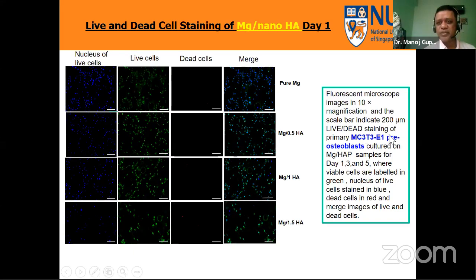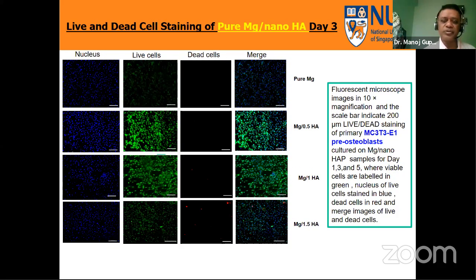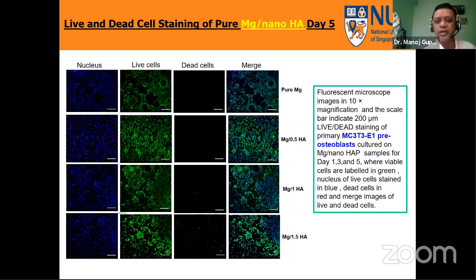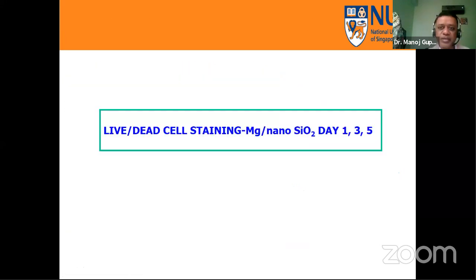Again using the MC3T3E1 pre-osteoblast cell line, all compositions show a very good presence of live cells. This is day 5 for nanohydroxyapatite, and apparently the best density was again for 0.5 HA and 1 HA. But 1.5 HA, shown in the bottom picture, is also very reasonable. Still, when compared, 0.5 and 1 are the best.